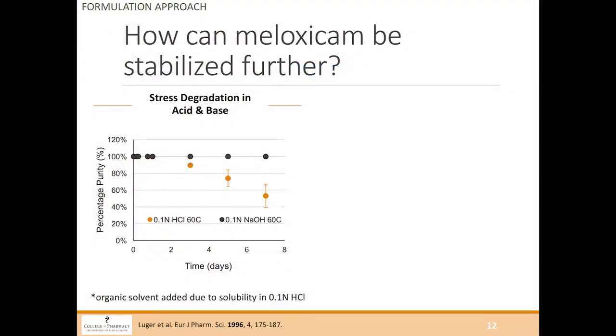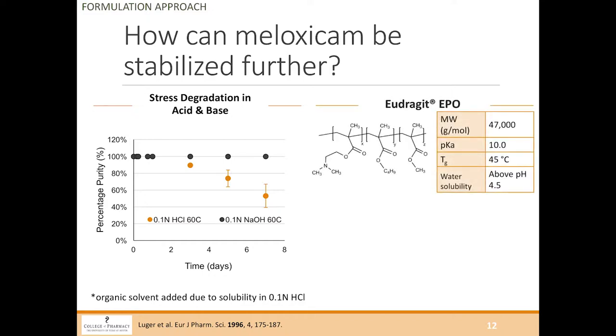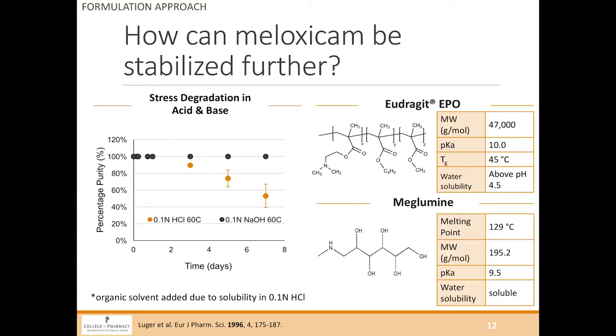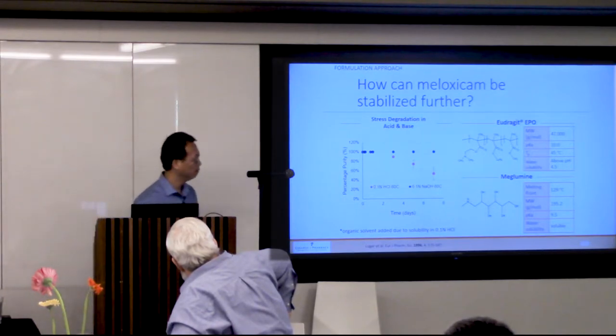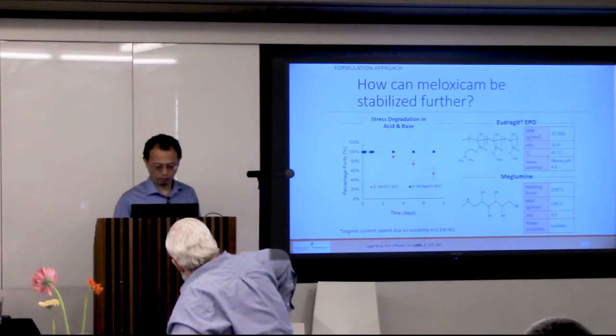And here's an example, we're looking at solution state stability. In 0.1 hydrochloric acid, 60 degrees C, they drop like crazy. But then you go to high pH, when that OH group is ionized, it's very stable. So we thought, why can't we just put something that would react? We thought of two materials. One is Eudragit EPO, which has a tertiary amine group. Right? It's right here. Another one is actually meglumine. Now meglumine is actually used as a common excipient in several pharmaceutical drugs. And what's interesting, if I look at pKa, we know they're going to react. Okay?